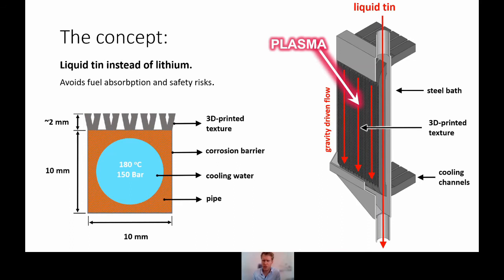We inject liquid tin from the top, and gravity is just slowly going to drive that to the bottom. Very, very slowly, actually, because there is a little bit of viscous drag, but also there is magnetic drag, which is very significant because of the high magnetic field. And then there is the coolant going through the pipes. That is roughly the layout.